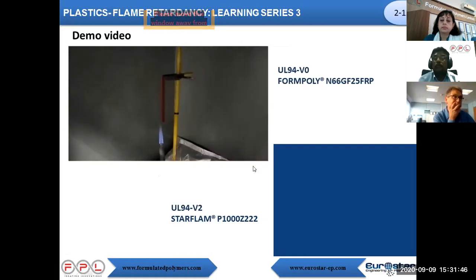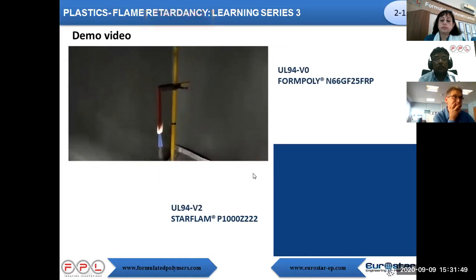We are seeing the UL94 V0 test, which is now performed using Formpoly N66GF25FRP material. The test specimen is positioned vertically in the holder. The specimen is ignited using the burner for 10 seconds. Withdraw the flame, count afterglow time and record. Flame the same specimen again for 10 seconds, then record afterglow time. This procedure repeats for 5 sets of specimens.